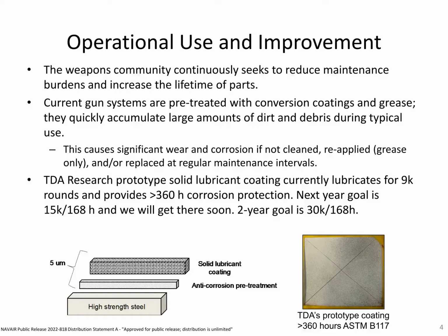The reason that this coating is of interest is because the current coatings to protect these gun parts really don't offer that much protection. The steel used are different types of high-strength steel, 4140, 4340, and stainless steel. And they are pre-treated with conversion coatings, which are coatings that go on the surface of the metal and deposit a thin layer of a metal oxide that protects the surface from rusting. They get a top coat of grease, and they basically have to get serviced every several thousand rounds, and the parts wear down pretty quickly.